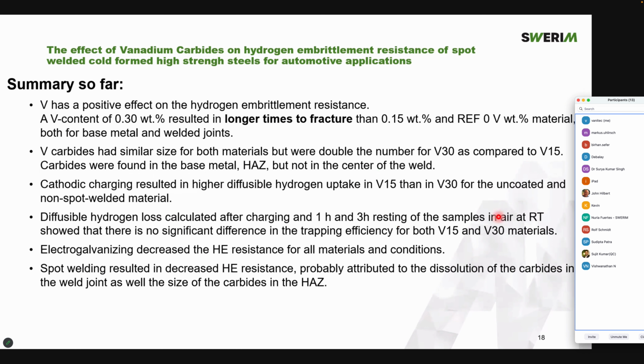So here we can summarize the results so far. We have seen that vanadium has a positive effect when it comes to hydrogen embrittlement resistance. A vanadium content of 0.30 weight% in those alloys had longer times to fracture in the test I just showed, compared to the reference material and the 0.15 weight% material. That applies both for the base material and also for the welded joints. When looking at the carbide sizes, we had similar sizes for both materials, and about double the number for 0.30% compared to 0.15%.